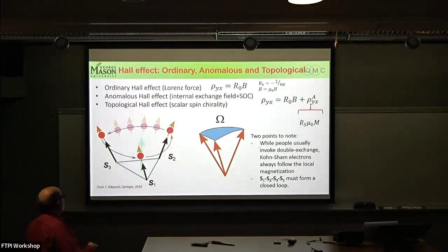So probably most of you know this classification of Hall effects, which is very often abused, I would say. There is this sort of mythology that the ordinary Hall effect is proportional to magnetic field and the anomalous Hall effect is proportional to magnetic moment, which is absolutely not true. It comes from the 1930s, when people were working with multi-domain materials, and magnetization and the anomalous Hall effect, for completely different reasons, are both proportional to domain imbalance. So this is plainly wrong.